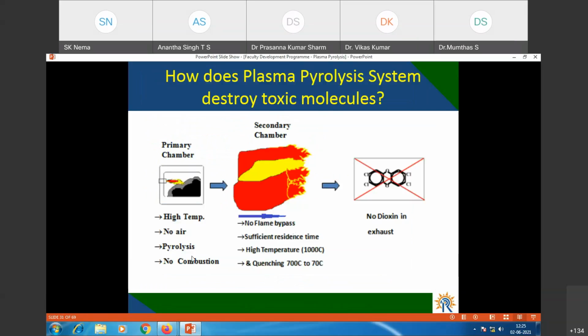So basically, how does the plasma pyrolysis system work? How is it destroying the toxic molecules? You can see here in the primary chamber, your temperature is high. You can easily maintain 1000 to 1200 at the wall, but near the plasma, the temperature is of the order of 5000 degrees centigrade. So high temperature is there, and then no air, we are not adding air, and pyrolysis is going on.